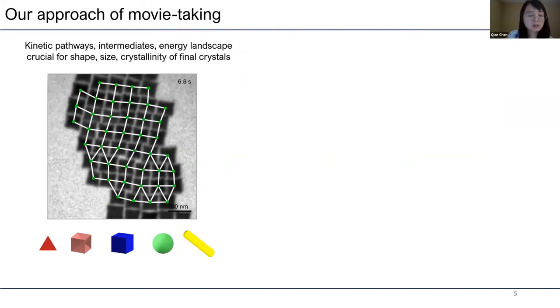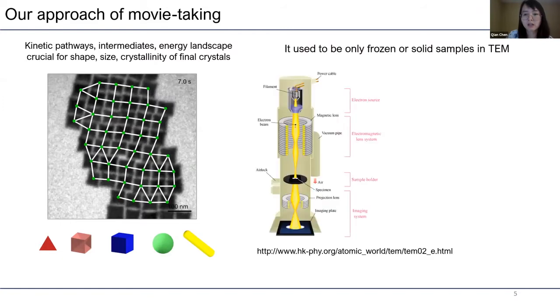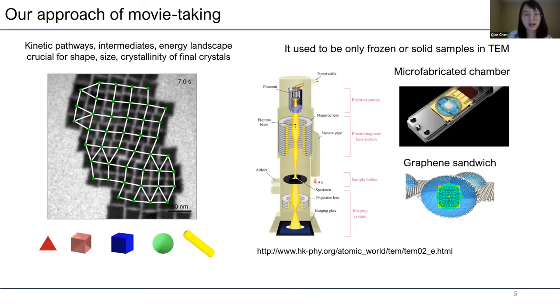The reason why such movies have been difficult to capture is that for a long time, the nanometer-resolving transmission electron microscopy, or TEM, has not been compatible with a liquid sample due to its high vacuum working condition. So here comes my group's unique expertise, together with the whole community's effort on liquid phase TEM, which allows you to image a liquid sample against the high vacuum of TEM. You can use a microfabricated liquid chamber, or you can use two graphene layers to sandwich and seal a liquid sample in between. So the idea was to use liquid phase TEM to watch crystallization in real space.